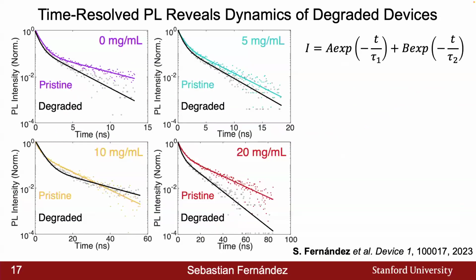Now looking at the time-resolved photoluminescence decay, the measurement setup here is that we take a fresh device, measure its photoluminescence decay, followed by 1 hour at 10 milliamps per centimeter squared of identical electrical operating conditions, followed by another scan. And we can see that all of these measurements can be modeled by this bi-exponential decay model, in which the lifetimes here, tau1 is a faster non-radiative recombination that is more associated with the grain boundaries within the perovskite thin film, while tau2 is a longer, more emissive, more related to radiative recombination pathway.